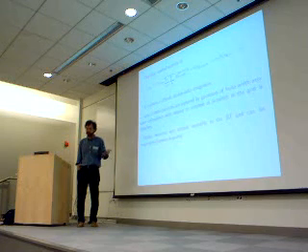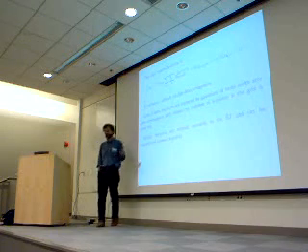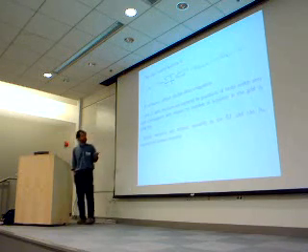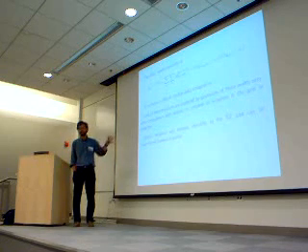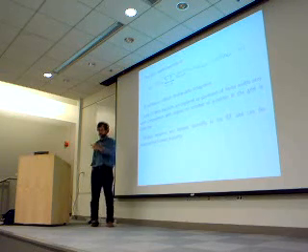And so when we deal with metals, we use some smearing technique. Typically, we are not using pure Gaussian smearing, but we use Marzari-Vanderbilt or Methfessel-Paxton smearing. Instead, when we calculate this integral here, we just use simple Gaussians, and so there is not much relationship between this delta and the smearing that we have used in the self-consistent calculation.